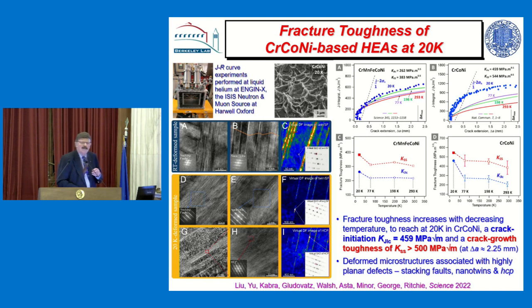But the interesting thing is that this material, this three-component chrome cobalt nickel, has a toughness of above 500 megapascal root meters at liquid helium temperatures, which is the highest toughness ever measured. So these are really interesting materials. They have peculiar properties, but these are the face-centered cubic ones, and they have the highest toughness of any materials.